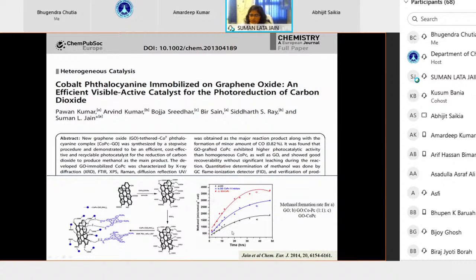So these are our reports. If we look at the comparison, this is the bare graphene oxide, this is the physical mixture of graphene oxide and cobalt phthalocyanine, and this is our immobilized system, where our complex is chemically attached to the graphene oxide. We can easily see the difference. This hybrid system has a significantly higher yield of methanol in comparison to both the bare semiconducting support as well as the physical mixture.